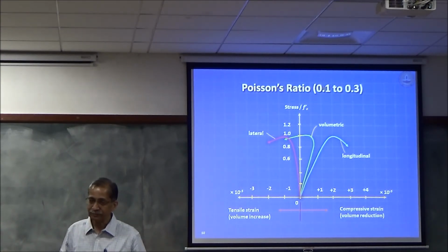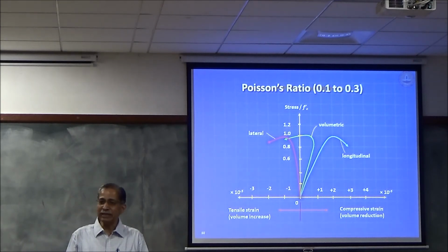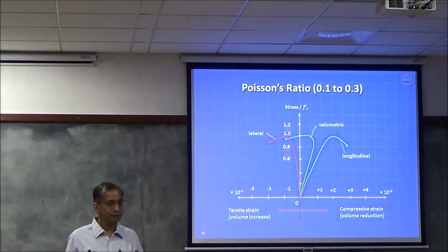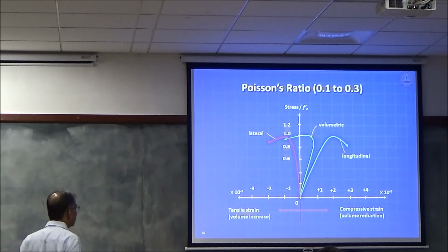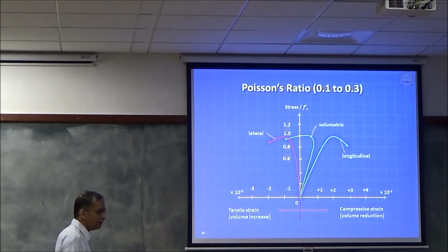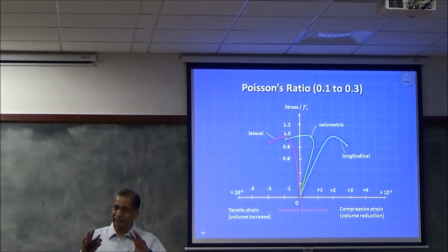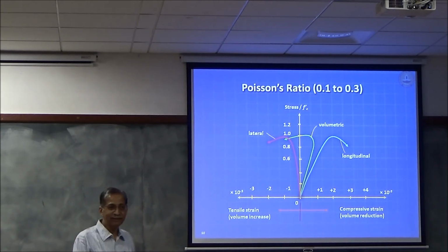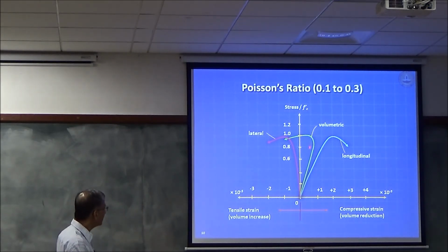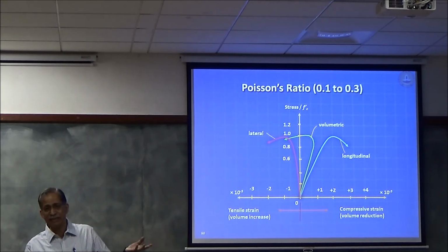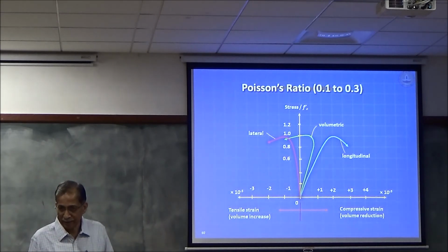Got it? We'll also look at what's happening to the volume change. So that's a volumetric strain. You find the volume initially becomes less until the bulging is so much that it switches from compression to tension. Broadly, this is the behavior. We can intuitively understand this. Clear?